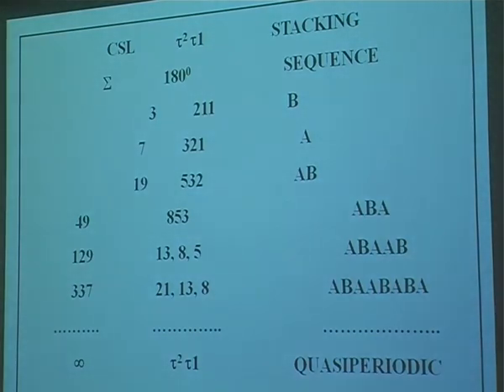This is something I talked about the last time I was here at Technion. If you get a twin with an index of 3 coincidence site lattice, to which Wayne Kaplan made a reference, it is twinned around [211] by 180 degrees, and if you call it the stacking sequence, it has a unit called B. If you twin it around the [321] axis, then you get 1 in 7, and we call it A. By mixing these two units, A and B, just like we do the Fibonacci sequence, we get the next one as [532]. You can see the indexes add up to that. We get 1 in 19 as the coincidence points, and the sequence is AB, AB, AB. So we can go on to 49, 129, 337, and of course right up to infinity.